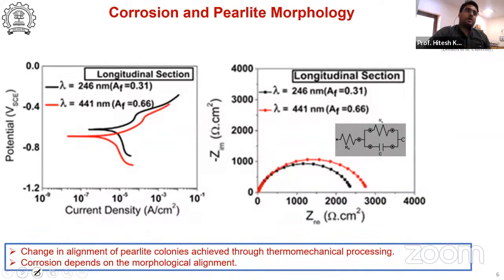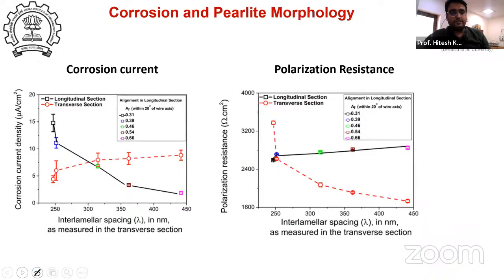Is it true for aqueous corrosion? In aqueous corrosion, we chose different solutions: H2SO4, as well as HCl and NaCl, all three. We can see that when we are increasing the alignment, there is a sudden drop in the corrosion rate of the material. The change in alignment of pearlitic colonies is changing the corrosion behavior of the material also. We calculated the Ecorr, Icorr, and Rp, the polarization resistance, in comparison with interlamellar spacing, because by changing the alignment, we are changing the interlamellar spacing also. So this is also affecting the oxidation. Earlier it affected the oxidation, and parallelly it affects the corrosion behavior of the material.